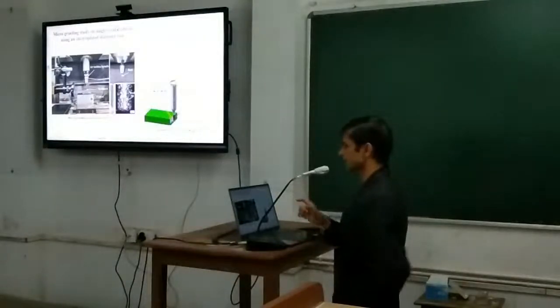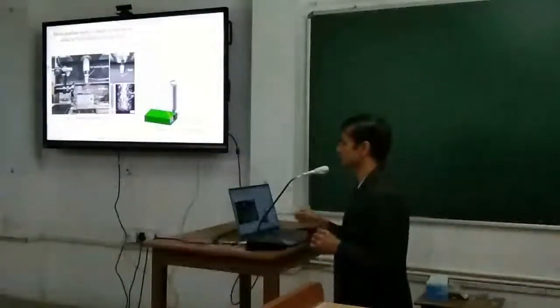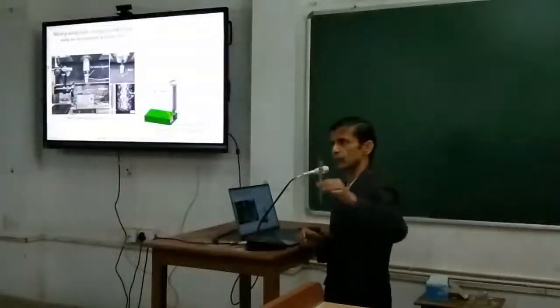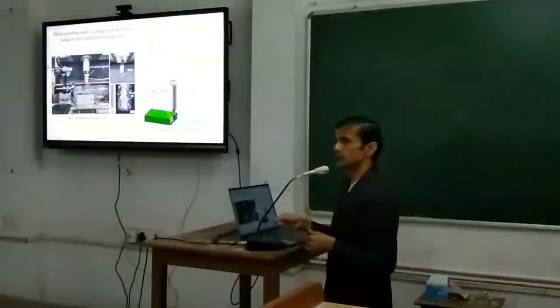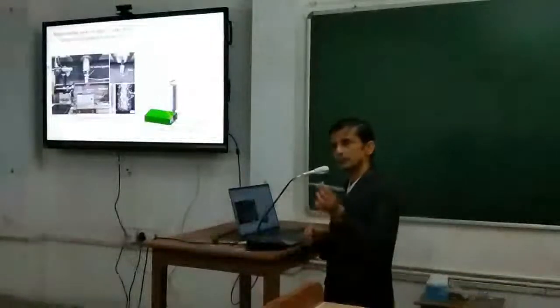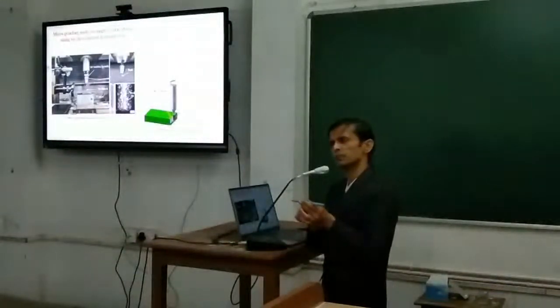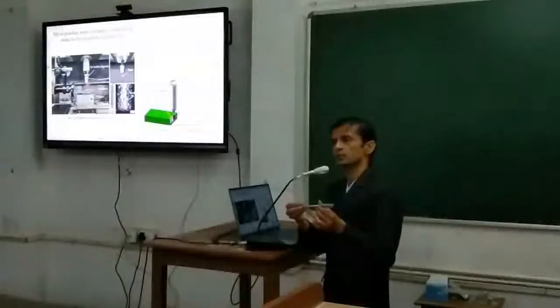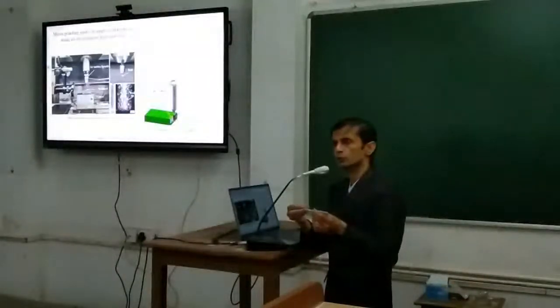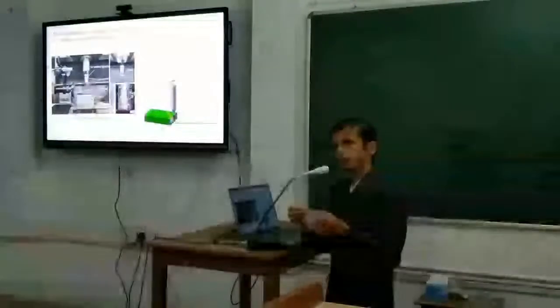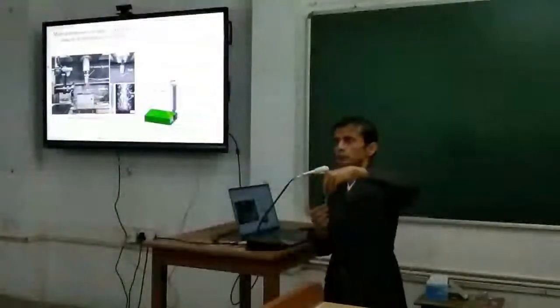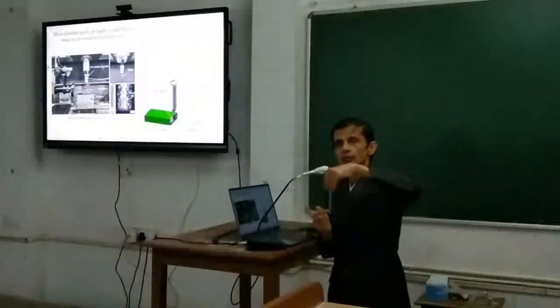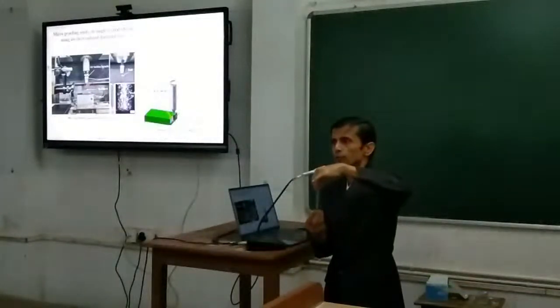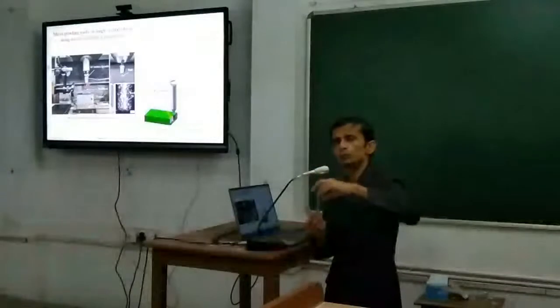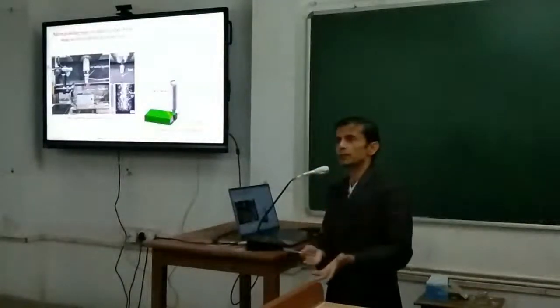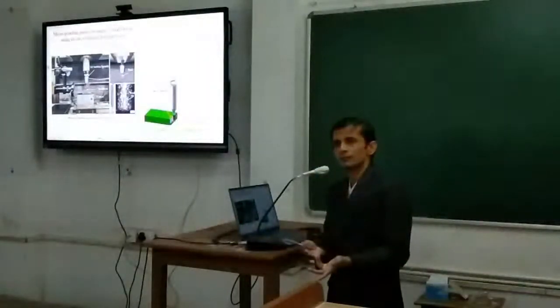But see, this grinding tool, whatever you are going to fix here, was made somewhere else. You take it out and fix it in the machine here. The moment it is in that machine, it shows very close to nanometric level accuracy in the eccentricity, the runout, if you talk about geometric dimensioning. But if you take out the same tool and fix it in the micromachining center, you can see a 5 micron runout. And that 5 micron runout, if you rotate it at 1 lakh RPM, would be a dynamic eccentricity in the order of 20 micron. And don't expect micromachining or micro grinding with the help of that.